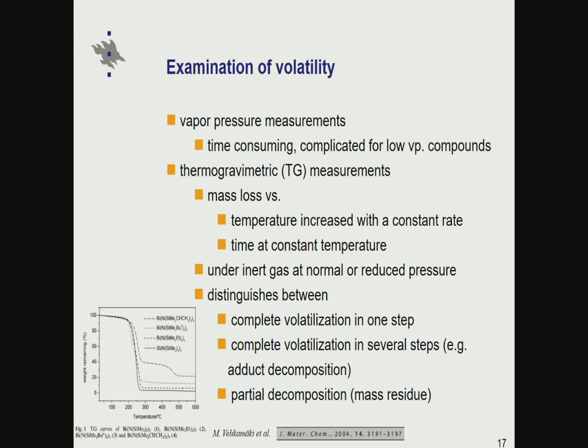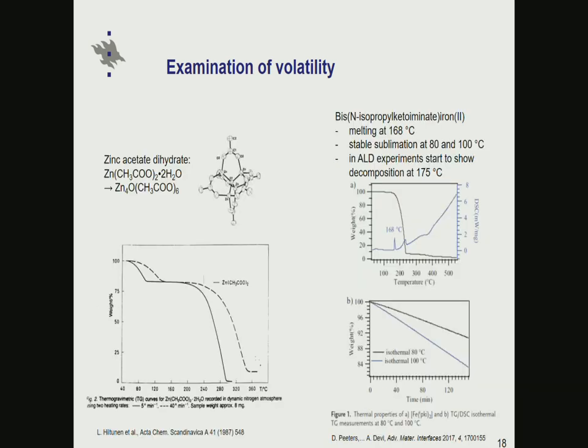But sometimes we see curves like this one, where there are a couple of steps, and in this case the residue is something like 30%. This is an indication that most likely this is not a very good ALD or MLD precursor. There seems to be partial decomposition taking place already during the volatilization.